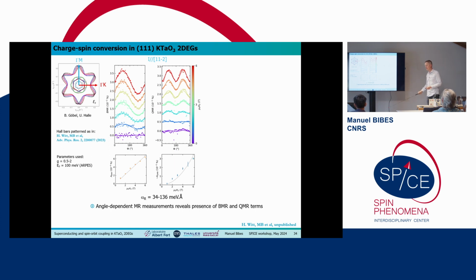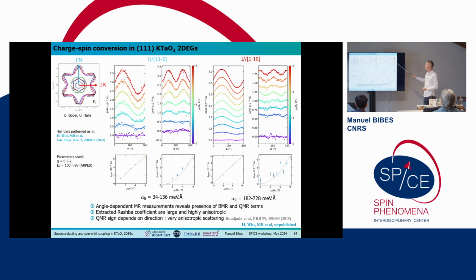So we again did these angular dependent measurements for the 111 2DEGs. The data are a bit more noisy because the mobilities are not quite as high as in the 001, but we see a linear dependence of this term with the magnetic field, as we should, and a quadratic dependence of the other term, as we also should. We do this for 2 different directions, and we extract some values which are, again, with a larger error bar because we don't know the g factor, but they seem to be larger than what we were estimating from ARPES. And we confirm that there's a quite strong anisotropy. I mean, the sign of the anisotropy is consistent with the earlier data. But it's really a pity that we don't have higher quality ARPES data. It's very difficult.